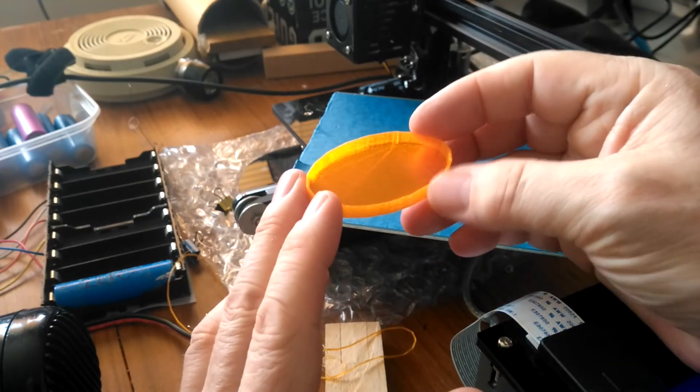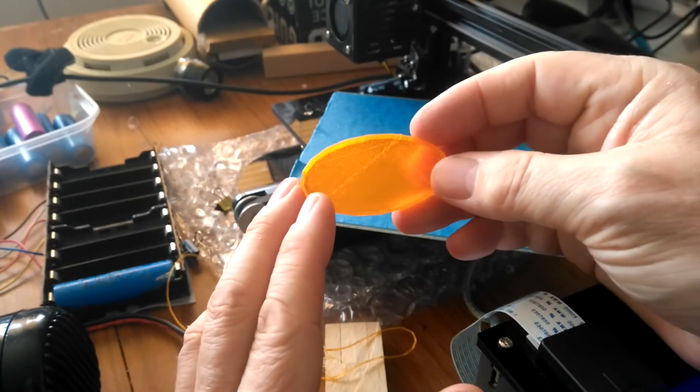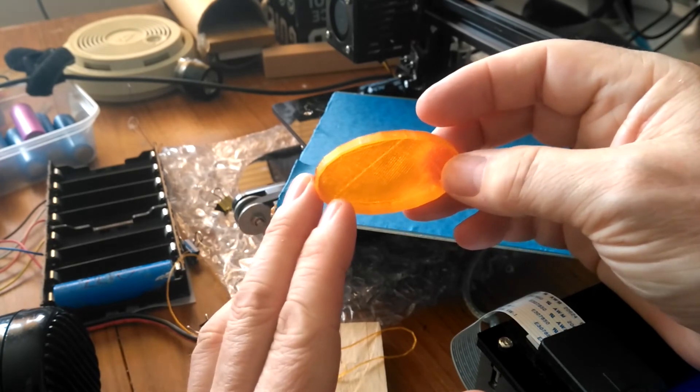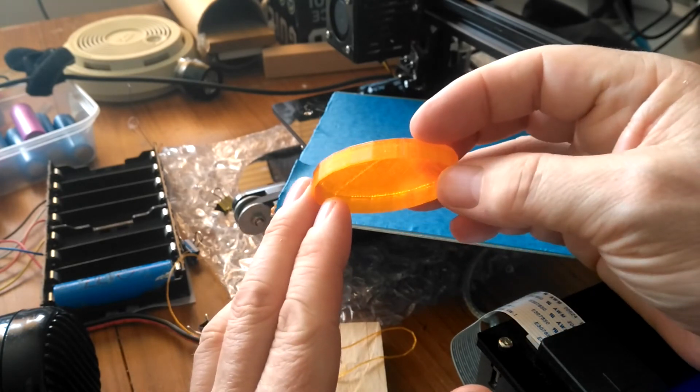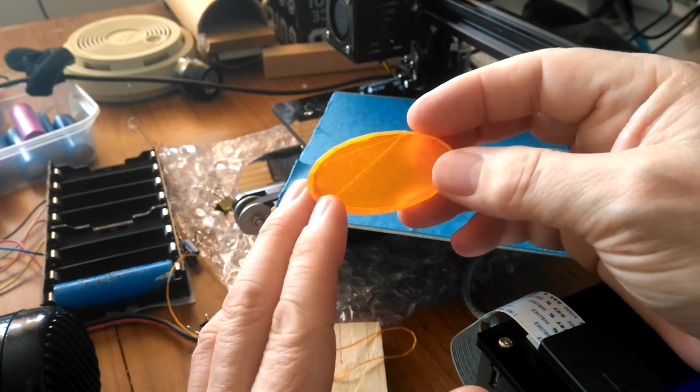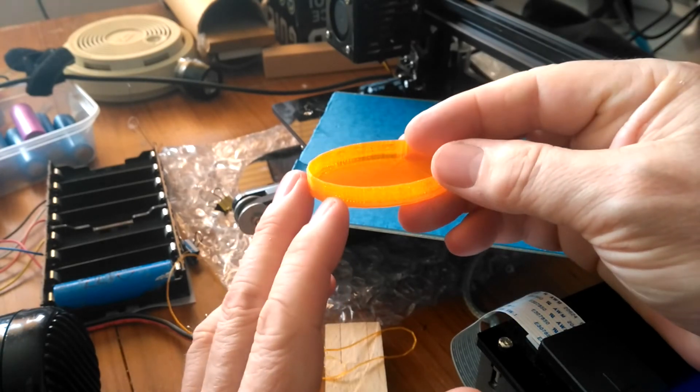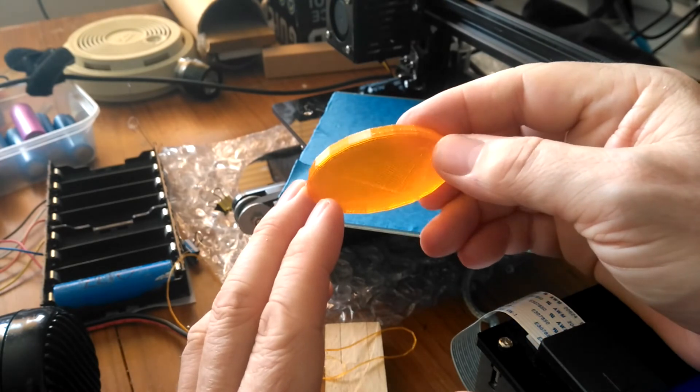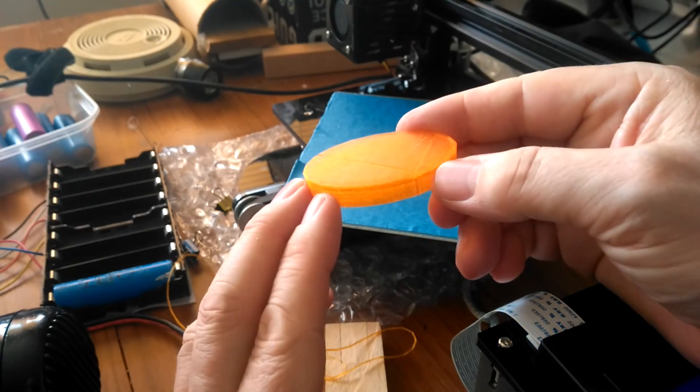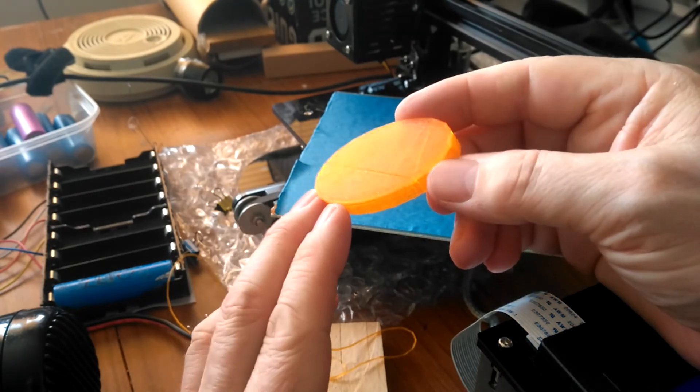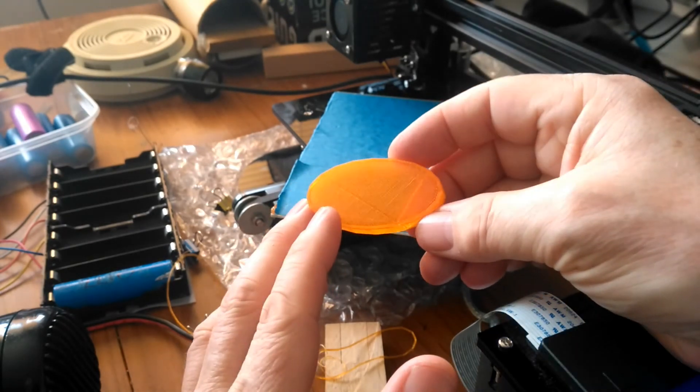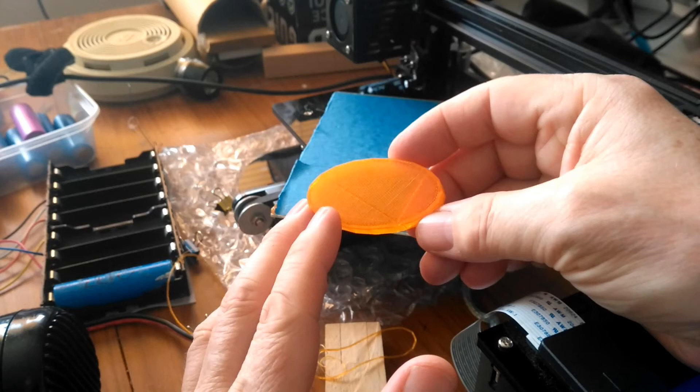I've adjusted the filament width. Its actual width is 1.64, I've adjusted it to 1.6, which is equivalent to upping the extrusion multiplier, and it just seems to be about perfect now. Well, there it is.